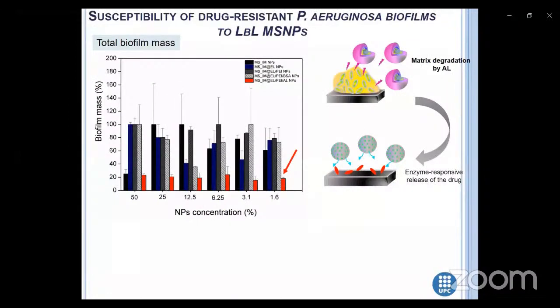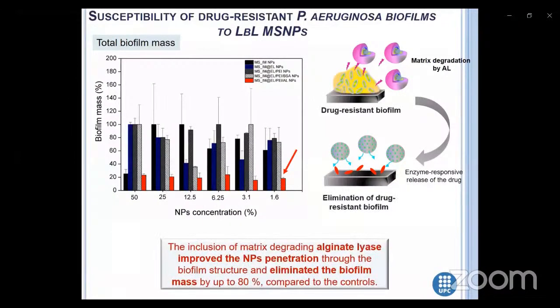So it was important to evaluate the ability of the nanoparticles to eradicate already established biofilms. High concentration of the drug-coated mesoporous silica nanoparticles would need to eliminate the drug-resistant biofilms due to the burst release of the antibiotics from the nanoparticles. However, only the layer-by-layer mesoporous silica nanoparticles with upper layer of alginate lyase demonstrated 80% reduction of the biofilm mass at very low concentration of the active agents.